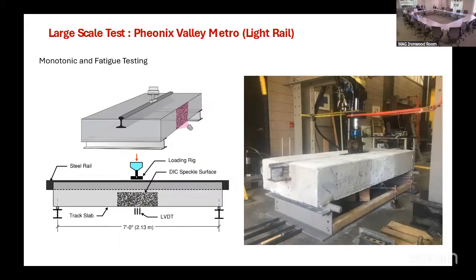So you just throw in every safety factor that you want to put in there, and also assume that there is soil loss support for this slab. So you're not counting anything on the soil's foundation support, and you're just basically providing the load as a 3-point bending beam. Apply the load on the rail. Now, to meet that 45 years, you have about 2 million cycles of service load that you have to apply. So we conducted the test as a fatigue test at twice the service load level for 2 million cycles. The entire test took approximately 8 days continuously, 24/7, to run the test.